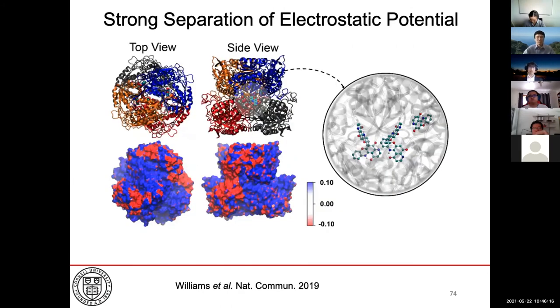And what we found is a very, very strong separation in the electrostatic potential, where a high electrostatic potential given by the blue regions indicates that there's a relative absence of electrons, and a low electrostatic potential given by the red regions indicates an abundance of electrons.